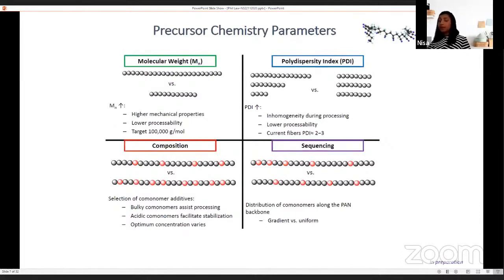So there is a strong demand on carbon fiber manufacturing industries to meet the demands arising from various sectors. But the challenge is, though carbon fibers have been known for more than 40 years, most of the details about carbon fiber production are still unknown, because the exact composition of each PAN fiber varies from one company to another and is generally considered a trade secret. So we only have some indications, like the quality of the carbon fiber is directly dependent on the precursor. About 90% of carbon fiber production is from polyacrylonitrile, or PAN, and this PAN will have 2 to 10% of co-monomer content in it.